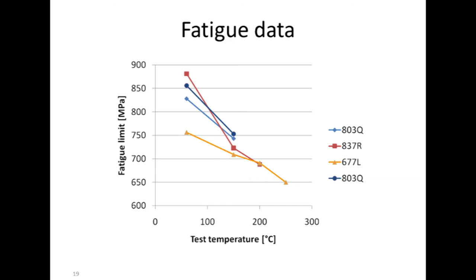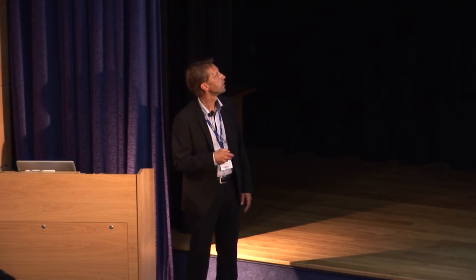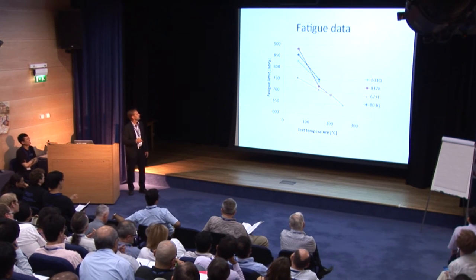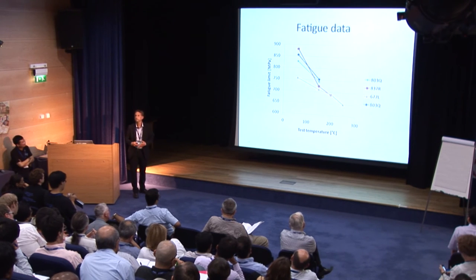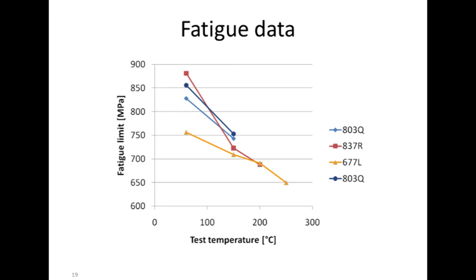I think different kinds of material, different kinds of microstructure will respond differently. And this is one way of looking at the material. How could you make a material more prone or more resistant to temperature? I think one interesting feature here, which is not written out, but I will tell you if you can keep a secret. No, kidding. If you look at those two materials, they are from the same heat, just heat treated differently. And this shows that you have the same inclusion population, but a difference in fatigue limit, which means the heat treatment and the microstructure will also affect it.